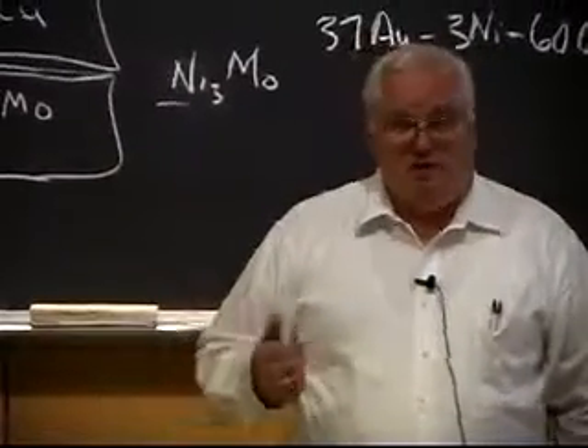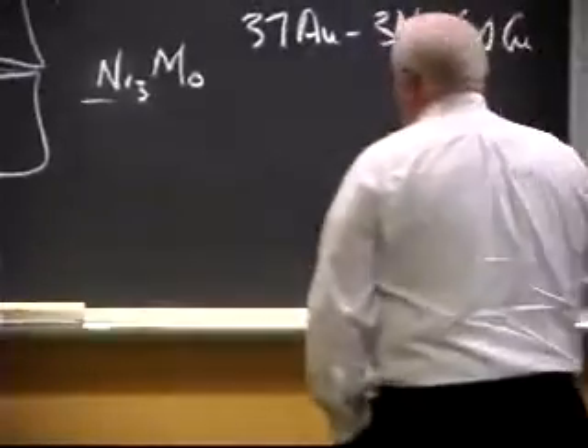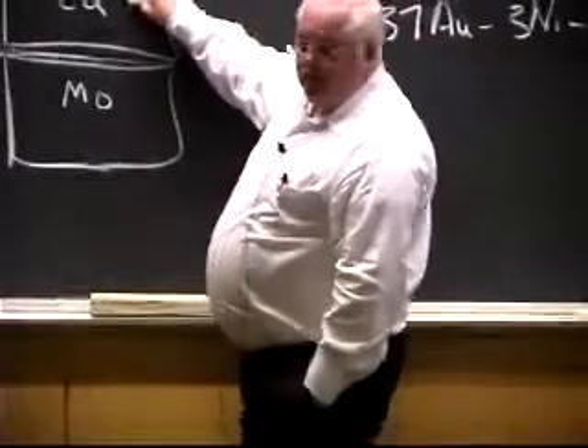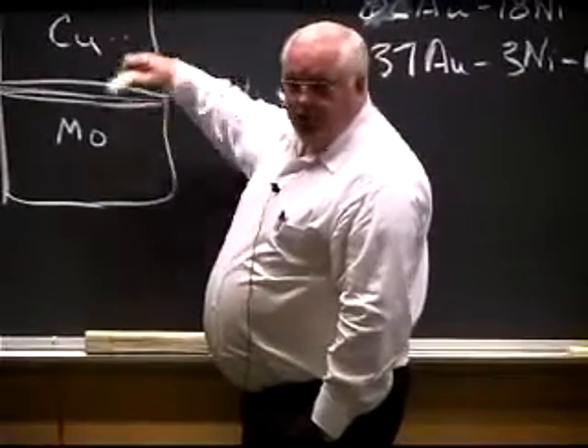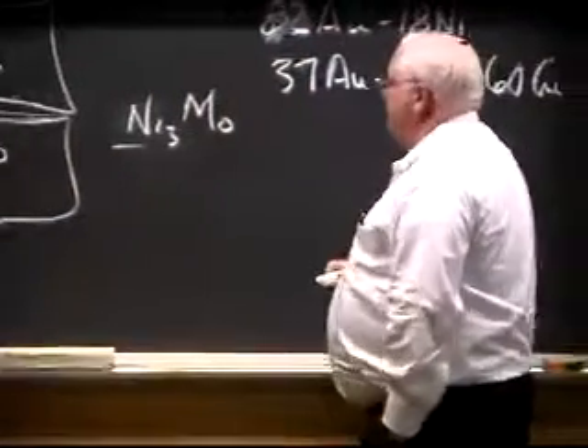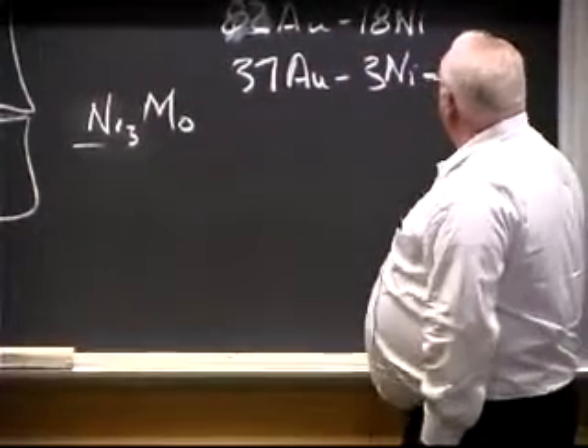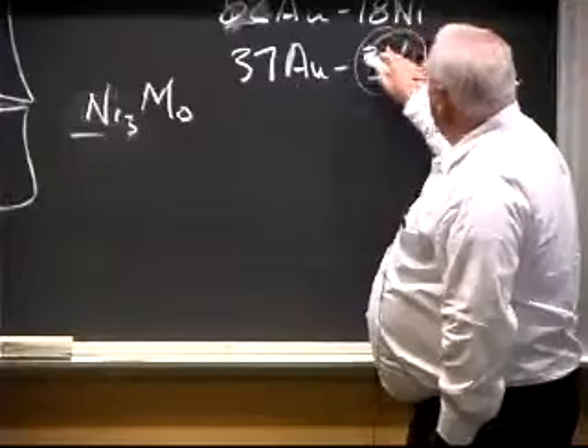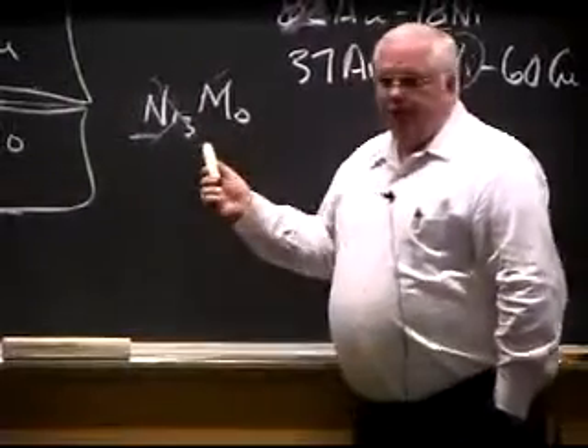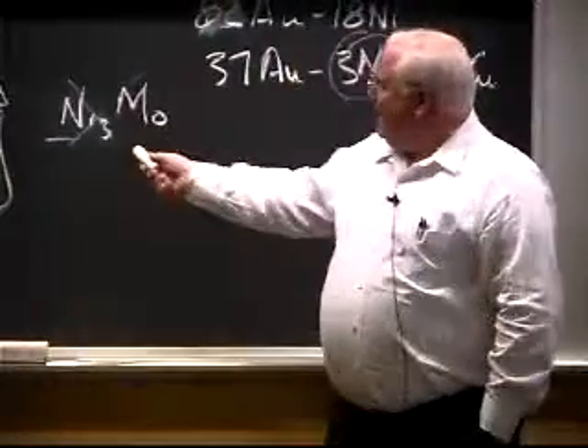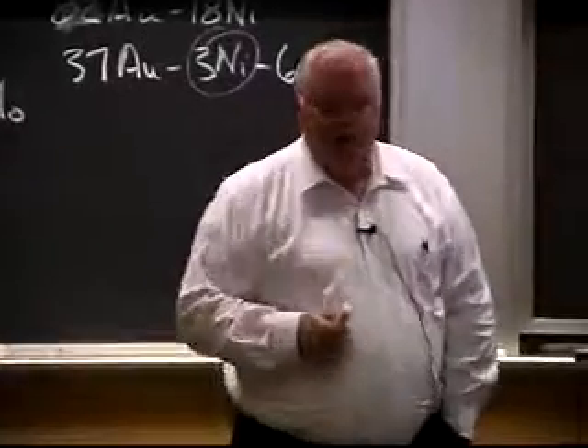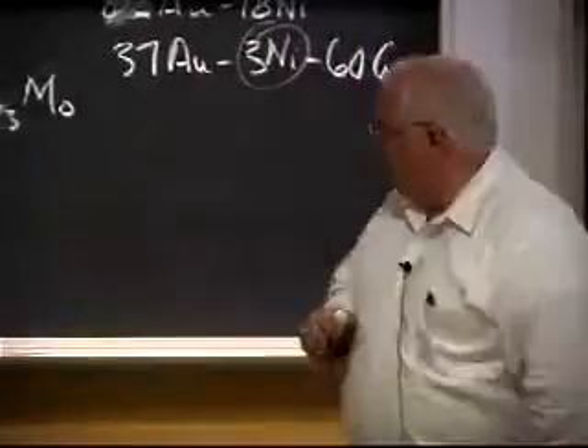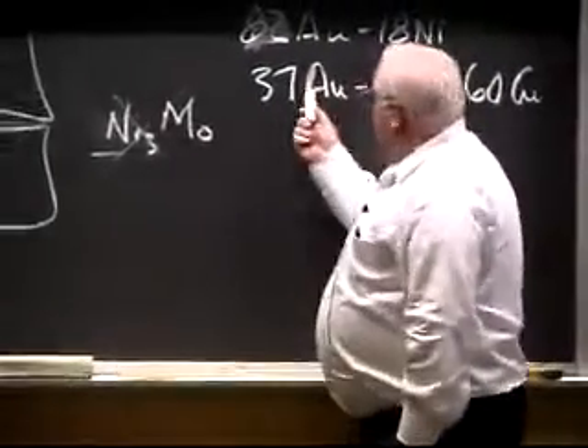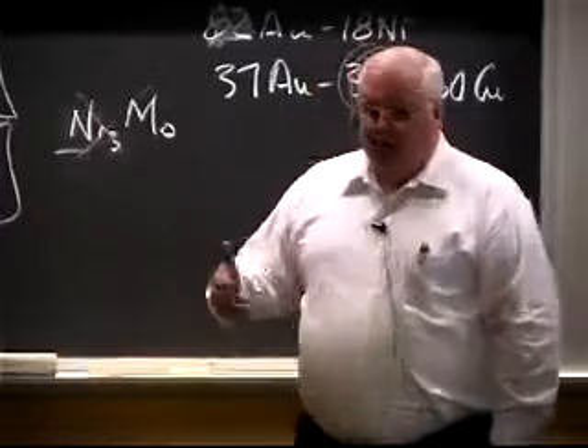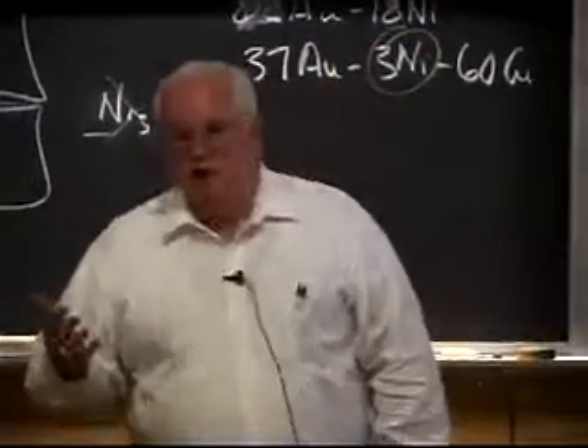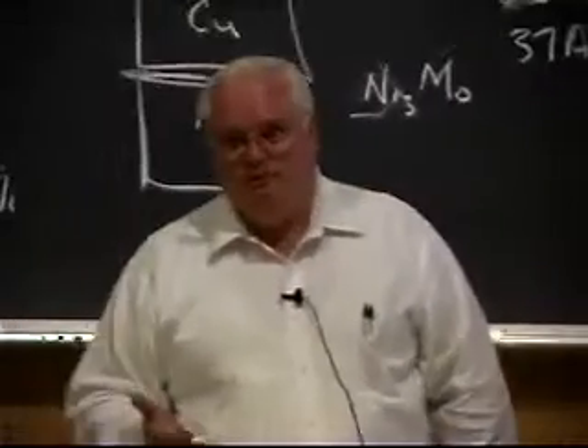And then I started thinking about the metallurgy. Well, what they had done is the gold was diffusing into the copper because copper and gold form a nice continuous series, leaving enough copper behind. The nickel was low enough that you wouldn't form the nickel 3 molybdenum. With low enough nickel, there's not enough nickel left over to form that intermetallic. The thermodynamic activity becomes too low in the nickel. The gold diffuses away, left a TLP bond, and it was a perfect bond. So they had actually solved the problem. They didn't know it, and they did.